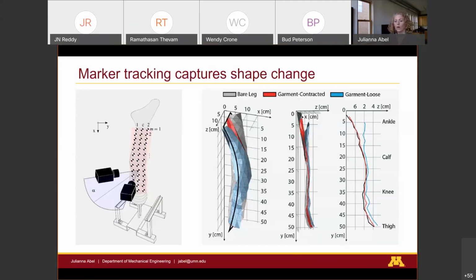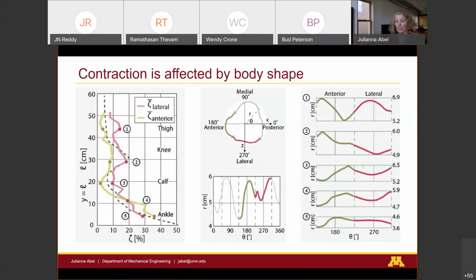And so we were able to quantitatively assess this contraction through image tracking using our Correlated Solutions VIC-3D system. And you can see in the gray is the bare leg, red represents the contracted form of the garment, and blue is the donned form, or the stretchy, flexible, cold form. And we can see the red and the black line match very well, so we're getting very consistent performance and contraction over the course of the body on the macro scale.